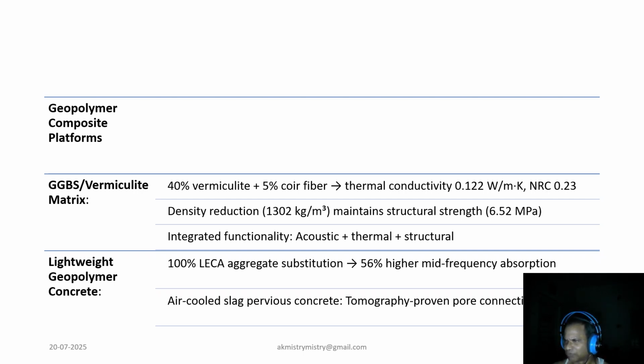Coming to the advanced slag material innovation, slag is not a one size fits all material. Its versatility shines in various innovations from lightweight geopolymer composites to pervious concretes. A matrix of GGBS and vermiculite with coir fiber achieves low thermal conductivity and dual acoustic thermal performance. Lightweight geopolymer concrete using LECA boosts mid-frequency absorption by 56%, which is a good value, and tomography confirms pore connectivity in pervious concrete ensuring both sound reduction and water infiltration. Each system serves a tailored function.